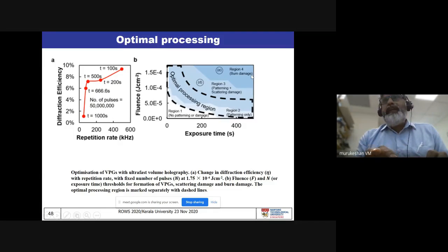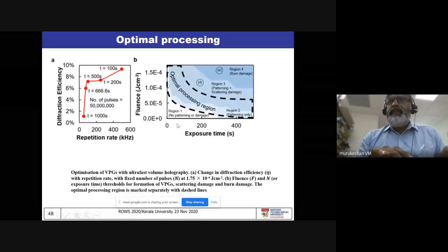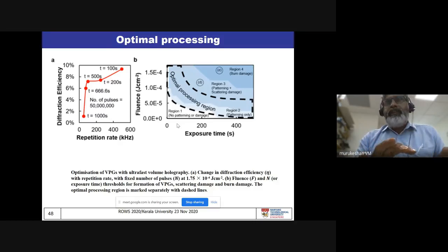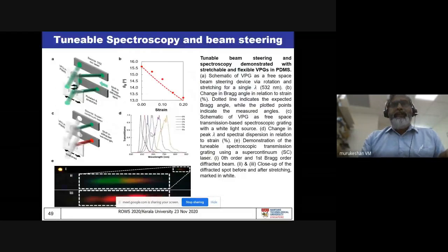It cannot be anywhere in this region 4 or region 3 or region 1. And it is a very, very important condition. So there is a lot of theoretical work done on that. Based on that, once you identify this region, you need to control the exposure time as well as the fluence that is required for getting such patterning, and you can actually get a very interesting pattern.